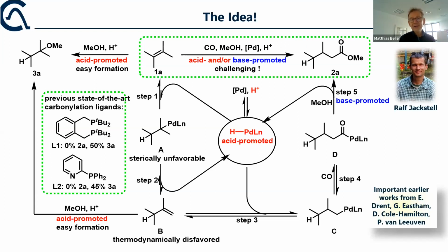Nevertheless, we know that there are metal hydride species, iridium, for example. This is the iridium-catalyzed hydrogenation of tetrasubstituted olefins, which are able to add a metal hydride to tetrasubstituted olefins. And therefore, we thought if we have a very active metal hydride with palladium as the carbonylation catalyst, it should be possible to generate this in situ. And if we generate this in situ, then even if it's not reacting, it will most likely undergo the well understood beta-hydride elimination. It can form the thermodynamic product back, but it also will give you this one, which is much more reactive than the original olefin. As I said, this chemistry is very well known and precedented, so it should be no problem to go to this. So initially we looked for metal catalysts which are able to allow for this step, because we thought this is the difficult step.